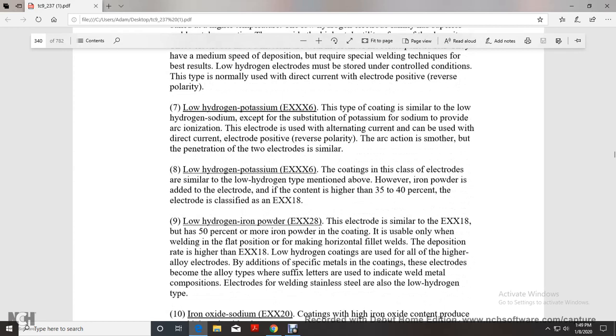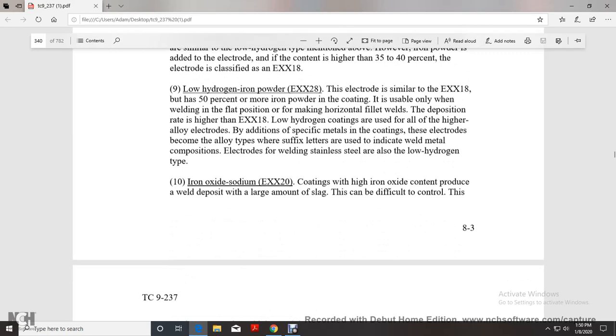Number 9, low hydrogen iron powder, EXX28: the electrode is similar to the EXX18 but has 50% more iron powder in the coating. It is usually used only when welding in the flat position, making horizontal fillet welds, with a higher deposition rate than the EXX18. The low hydrogen coating is used with all the higher alloy electrodes, and in addition, specific metals are added to the coating so these electrodes become the alloy type. Suffix letters are used to indicate weld metal composition. Electrodes that weld stainless steel are of the low hydrogen type.